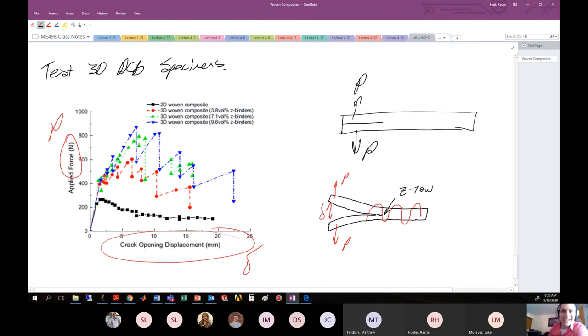At that particular point, it is going to take a massive, massive amount of energy to break open that toe. So think about ripping open a sample: you need insane amounts of energy to rupture through those fibers that are running in that third direction. Okay. And you're going to build a bunch of energy until that toe finally breaks, and then your crack just shoots forward like lightning after that energy has been released. So that's exactly what we're seeing in this load displacement curve.